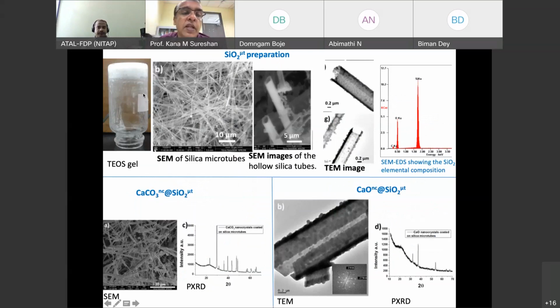This is the silica TEOS gel. This is the SEM of silica tubes. You can see they are hollow tubes after removing the gelator. And this is the TEM, transmission electron microscopy, showing hollow tubes with tiny crystals. And you can also characterize at each level. This is only silica, you can see from EDS, and this is the calcium carbonate stage, and this is calcium oxide. So at each stage, using powder XRD, you can characterize this material. So this is nanocrystals of calcium oxide on silica microtubes.